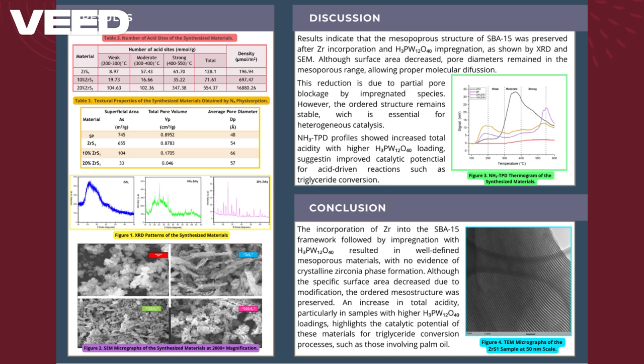Figure 4 shows the transmission electron microscopy (TEM) analysis of the ZR-S1 sample at 50 nanometers, revealing a highly ordered structure characteristic of zirconium-modified SBA-15. A uniform arrangement of parallel channels is observed, typical of the hexagonal pore structure of SBA-15. The incorporation of zirconium does not significantly alter the mesoporous organization, as the regular channel arrangement is preserved. No segregated zirconium oxide particles are detected, indicating homogeneous dispersion of zirconium within the silica matrix. This behavior is favorable for catalytic applications, ensuring efficient access to active sites without blockage of the mesoporous channels.